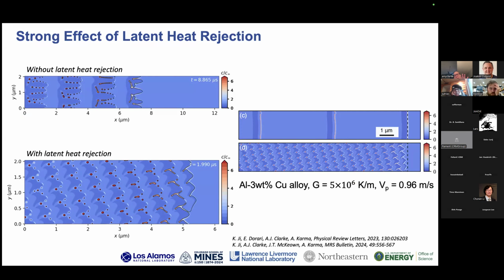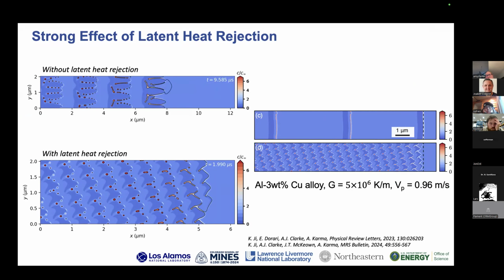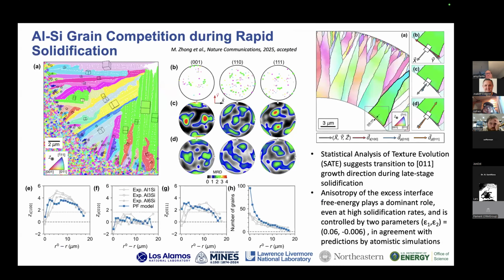So now that we have that newer model for rapid solidification that we validated with aluminum copper, we've been doing a lot more in this space more recently. So this is an example in aluminum silicon, extending some earlier work that we did on directional solidification, looking at grain competition, but now during rapid solidification. And the nice thing about DTEM is that we get the interface position with time. So we have an idea of where the interface is during the growth.